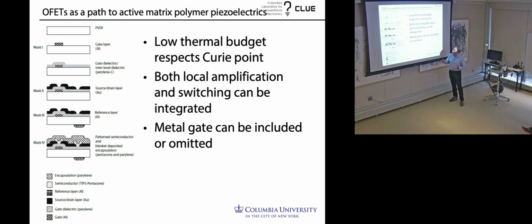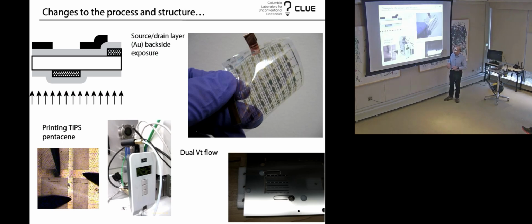And so by going through this flow, we can make switching transistors, and we can also make transistors that create what is effectively a charge amplifier for the piezoelectric material right there on the structure without having to route the charge, which then creates leakage and other challenges. If anyone's interested, we can get into the gory details of making the devices. There's lots to it, and we don't have to get that into it. But basically, the long and the short of it is, in order to get acoustic performance, we need to really squeeze all the knobs. We use 2 threshold voltages because we need a different threshold voltage in each transistor.